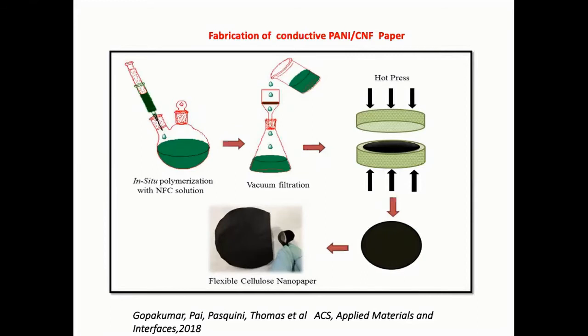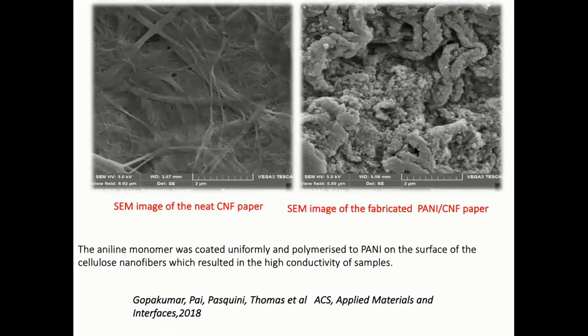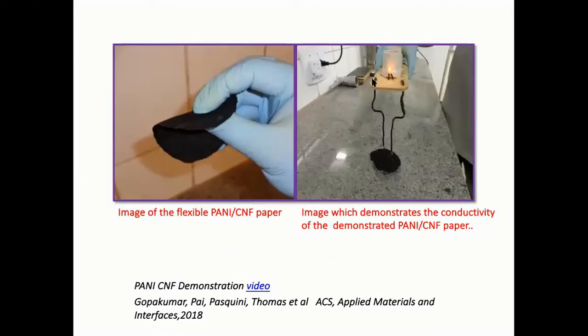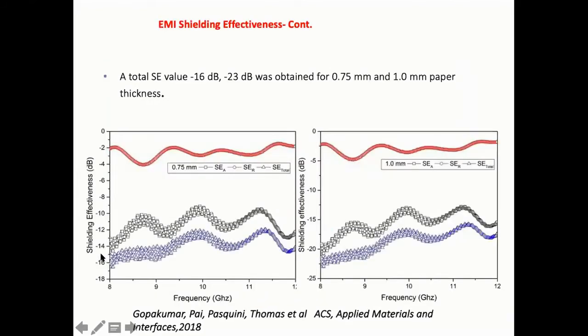What is the use of this material? You can see the next slide. It's extremely conductive. Look at the conductivity. And this is a wonderful material for electromagnetic shielding. Your mobile phone has a metallic shielder, and we have shown that this metallic shielder could be replaced by nanocellulose shielding material. Nanocellulose combined with polyaniline.